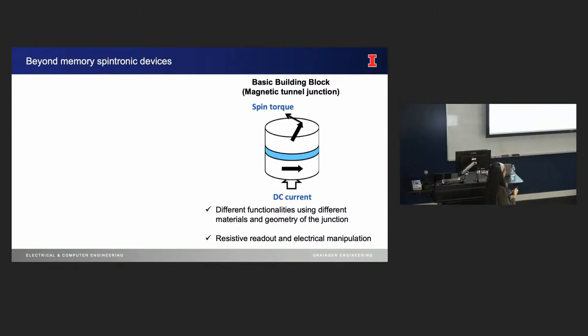It has two electrodes over here that are made out of a ferromagnet, and this blue layer is a thin tunneling barrier like magnesium oxide. So what happens in this MTJ is you pass the current and you control the orientation of the second layer, which is called the free layer. And once this free layer changes, the resistance of the stack would also change. So the resistance could be a low resistance or a high resistance depending on how the ferromagnetic electrodes are aligned with each other. This is at the heart of all of the magnetic memories that I showed earlier.